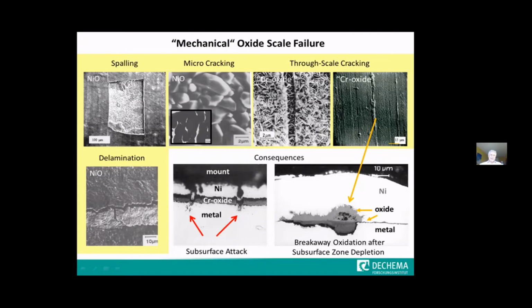And not only on a kind of macroscopic or pseudo-macroscopic failure scale as here, it can also happen on a submicroscopic scale, which means you need a TEM in such a case, for instance, to see that even micro cracks can occur between the grains of an oxide scale, as this image shows. The aggressive environment can permeate through the scale even via these micro cracks, although you have the feeling that this is a completely undamaged scale. So sometimes it can be enough to increase corrosive attack that you have such micro cracks in the oxide scale.